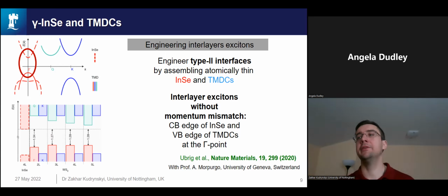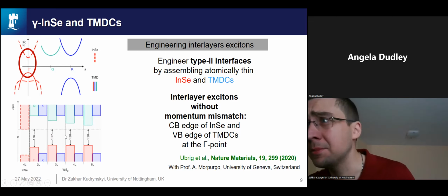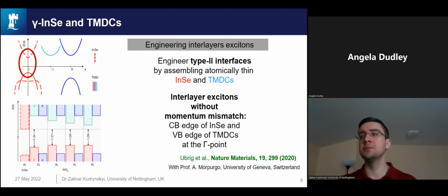And this enables the creation of an exciton without any momentum mismatch. And the excitons also have tunable energy, an energy that can be tuned by choice of layer thicknesses, as shown here, for example. Different excitons can be created by using, for example, 4-layer indium selenide with different layers of TMDCs based on tungsten disulfide. And this idea of interlayer excitons has been tested experimentally in collaboration with Professor Alberto Morpurgo from the University of Geneva in Switzerland. So the unique electronic band structure of indium selenide can be used in many different ways and in combination with different materials.